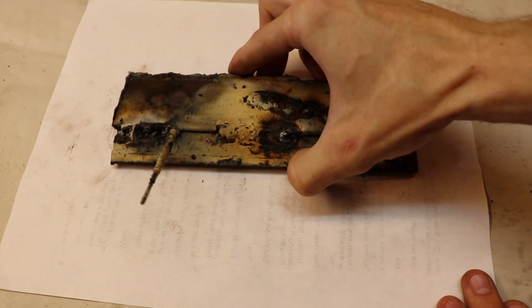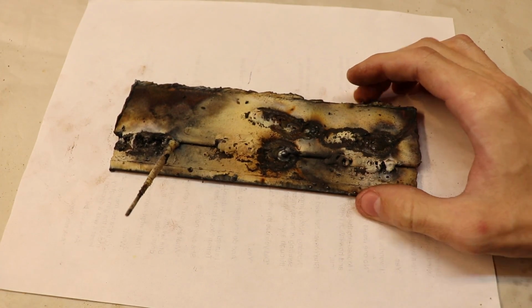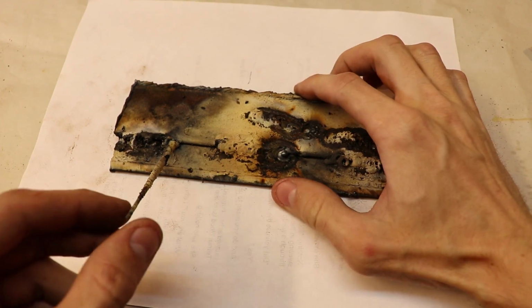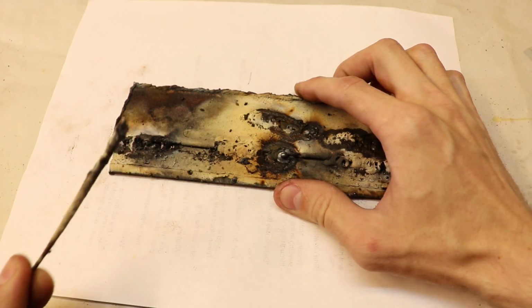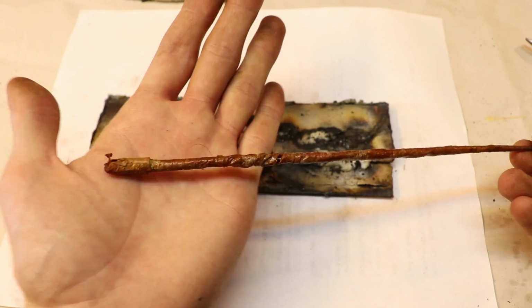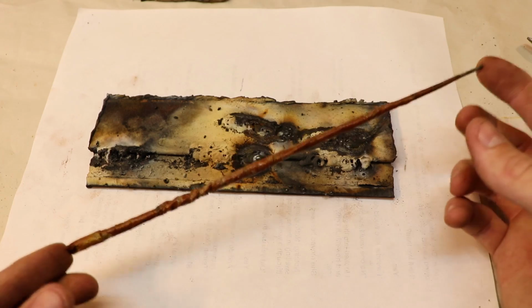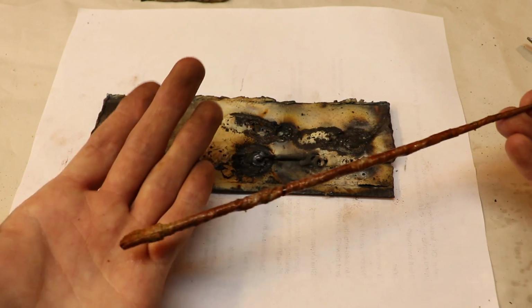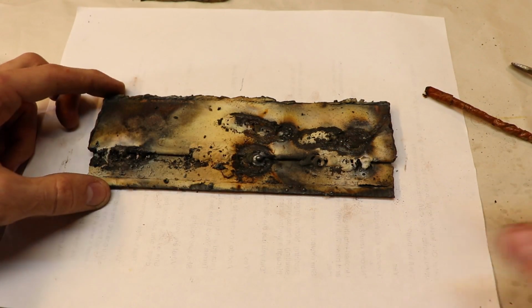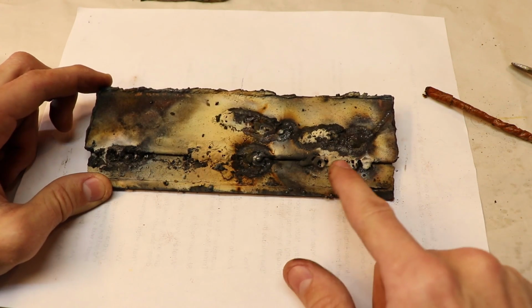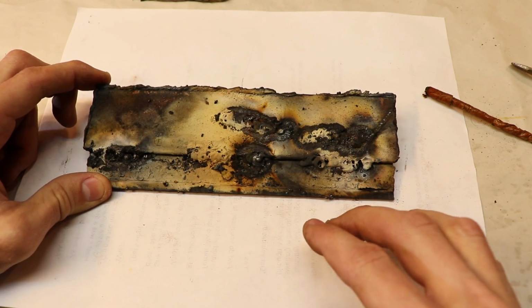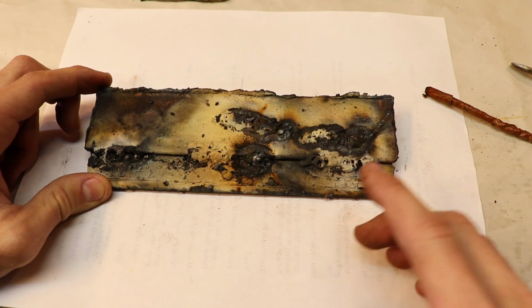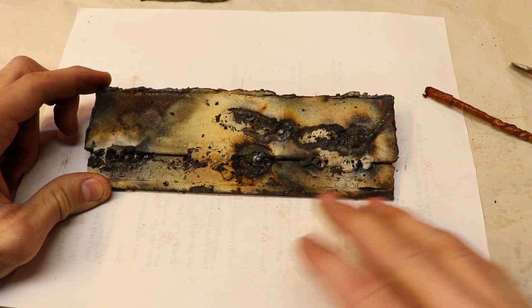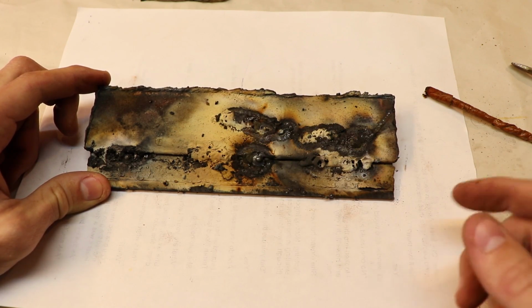Alright, and here's what I welded together with the sodium silicate rods. Oh, I might have left that on, sorry. Right, so these sodium silicate rods were actually pretty interesting. They did give me decent results. Now, first of all, notice how the plate itself has a lot of soot, a lot of ash on it, and there's barely any slag. There's, well, no slag at all.